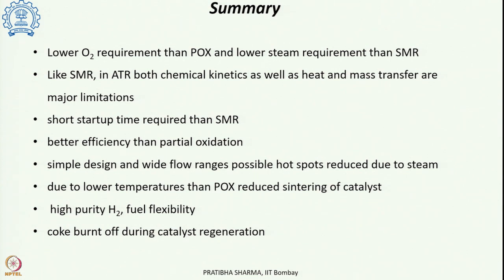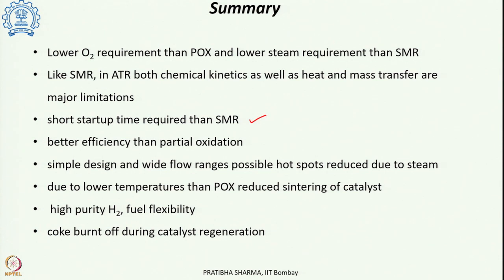Again, in the ATR process, the chemical kinetics as well as both the heat and mass transfer are the major limiting factors deciding the overall process. Compared to steam methane reforming, since no external heat exchange is required, as the heat required for the reaction is provided within the reactor, the startup time required is much shorter compared to the steam methane reforming process. It has a better efficiency compared to the partial oxidation, because the heat produced in the exothermic reaction is being used in the endothermic reaction. So, the thermal efficiencies are comparatively better than the partial oxidation.